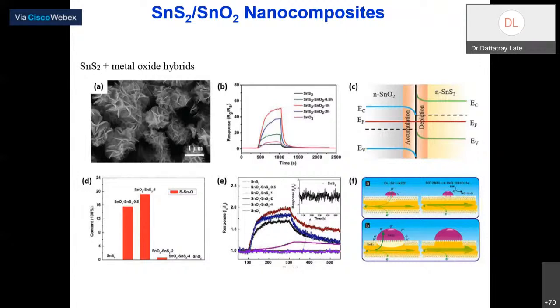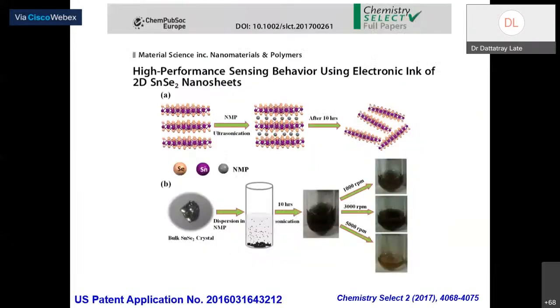Yes, of course. With the methodology which we adopted earlier, you can have a composite or hybrid material of SnS2 and SnO2 nanoparticles. SnS2 is a layered material and SnO2 is an oxide material. So when you have a hybrid material, you have large surface area available, and agglomeration of SnO2 nanoparticles is much less, with the opportunity of improved surface area, and that gives you very good sensitivity and selectivity. Here again, we have similar materials, but we have also filed a US patent based on this technology.